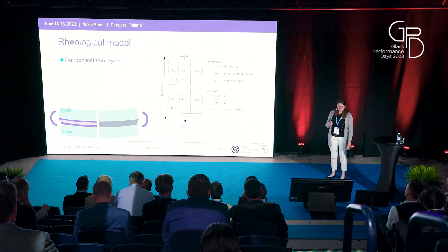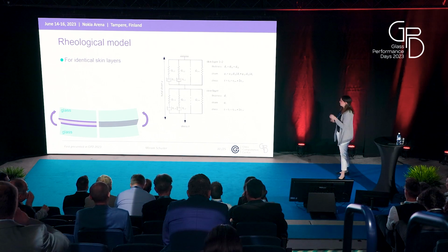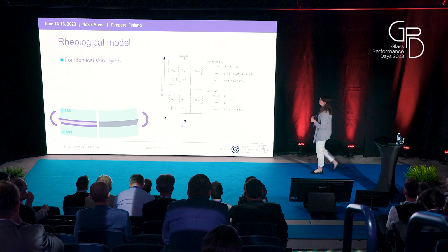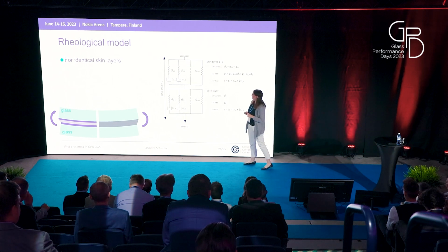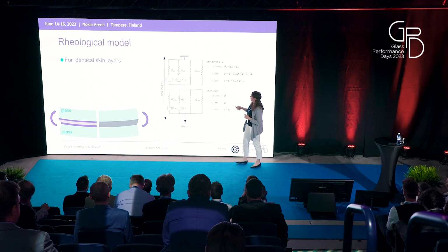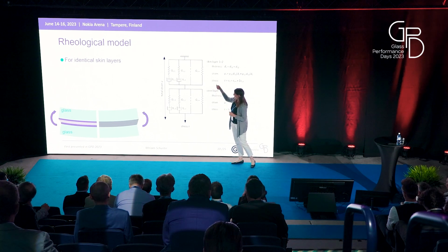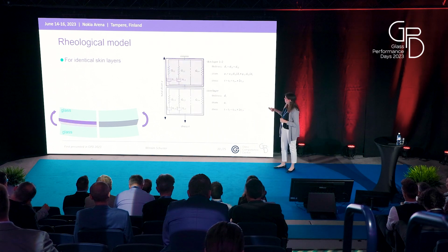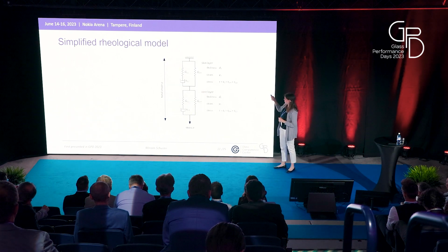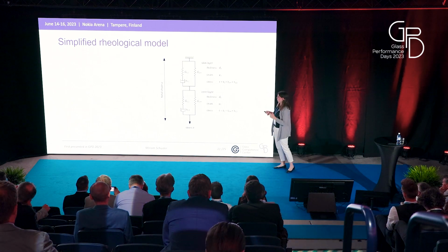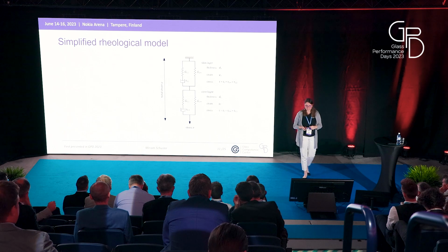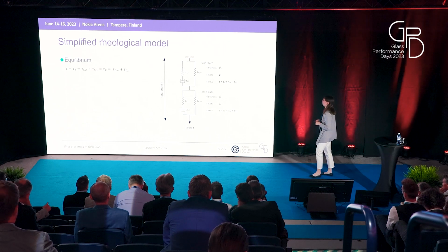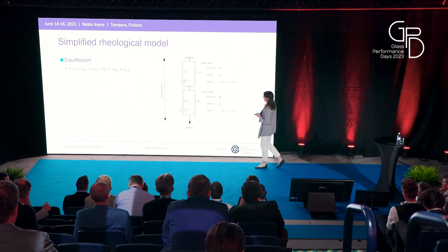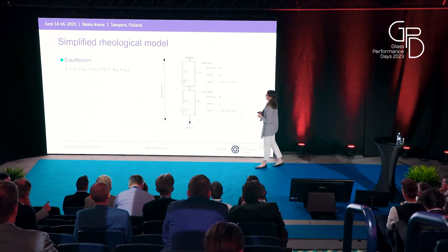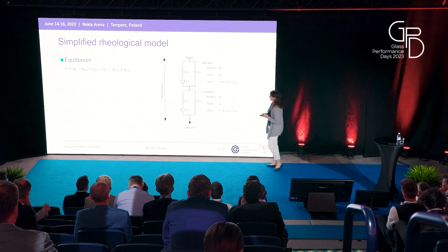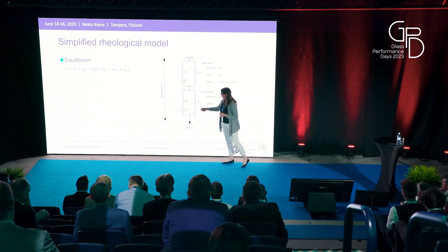In the next step, I tried to do some parametric studies with simplified models, and to further simplify, I decided to firstly only consider 1 Maxwell model per layer, which then looked like this. So we have the skin layer and the core layer, but with a reduced amount of parameters. And then the first thing I considered was equilibrium, which means we are looking at the stress, and we see that the stress in each of those layers is the same and consists of the sum of the stress in the elastic spring and the Maxwell element.